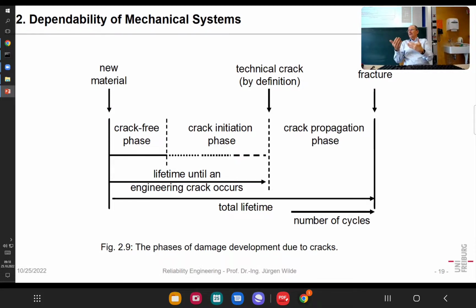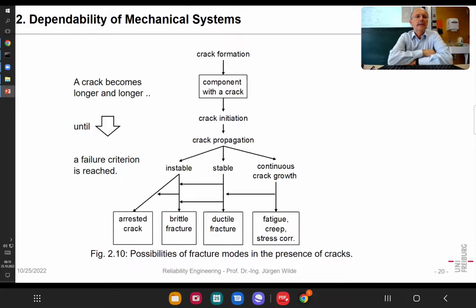immediately. So typically in a fatigue problem, you look at the cracked surface and you always find two areas: the fatigue area and the final crack area. And in that way, that's the phases of crack. And also it's interesting,